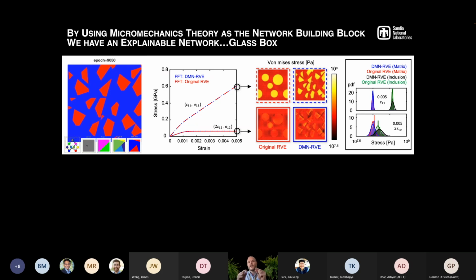The only difference is going to be in the tails. If you notice, the microstructure predicted by the network has these very sharp inclusions, which you don't have in the original RVE. And these sharp inclusions show up in the tail end of the distribution of the local fields.